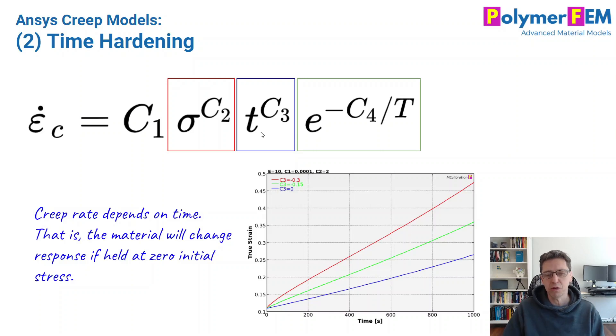So time is really weird because you don't want your material model to suddenly behave differently if it's exposed to zero stress conditions for different times. That just doesn't make much sense. So that's kind of cheating a little bit when you write the creep equation by including time directly in the creep equation. You need to be very careful when you use such a model in a finite element simulation, because many steps, depending on how long they are, will influence the creep response. So I try to avoid those where we have explicit time dependence in the creep equation.